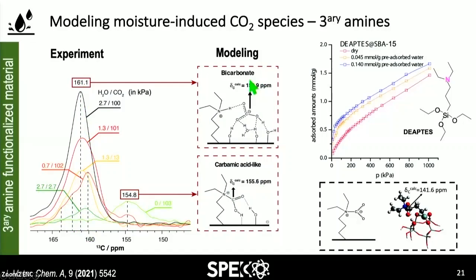We have also looked to see if we have some kind of species like this, where the N establishes a bond directly with the carbon, but that would have to appear at 141, considering the calculations, and we haven't seen that in the spectra, in the experimental data.